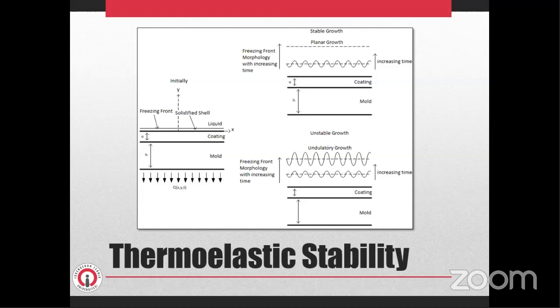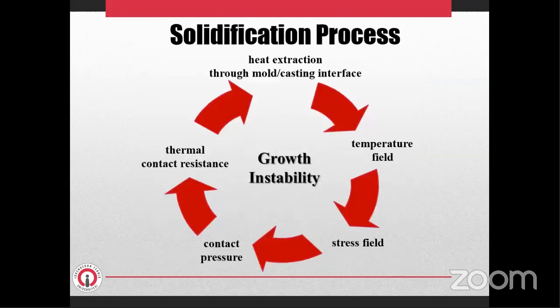Stable growth means that when small non-uniformities are added to the extracted heat flux, the amplitude of the undulation decreases to zero without increasing during this short time. If the amplitude of the undulation increases in this specific time interval, then this behavior defines unstable growth. And as mentioned before, when the mean shell thickness reaches sufficient thickness, these relations between the interface conditions again break off and the undulation decays. The closed loop mechanism of the solidification process is shown in this figure.